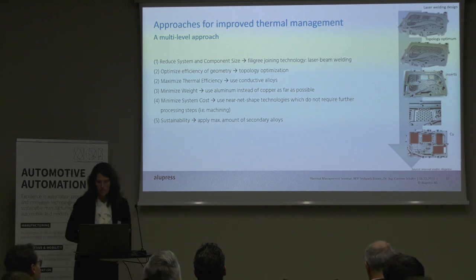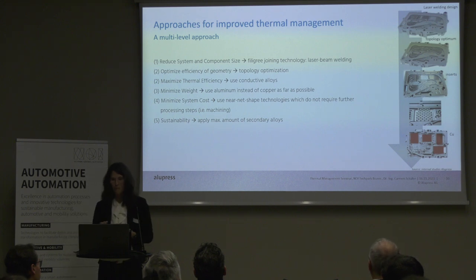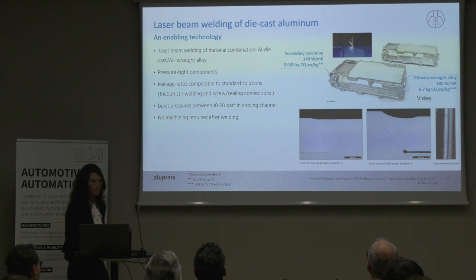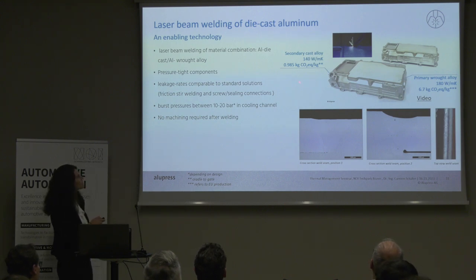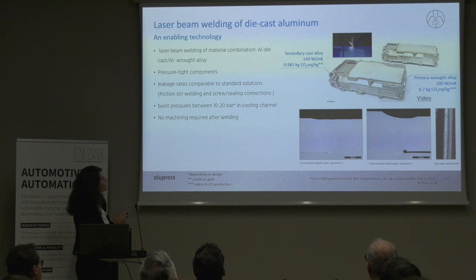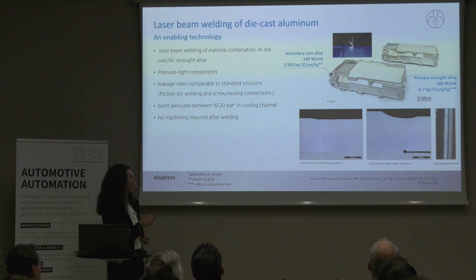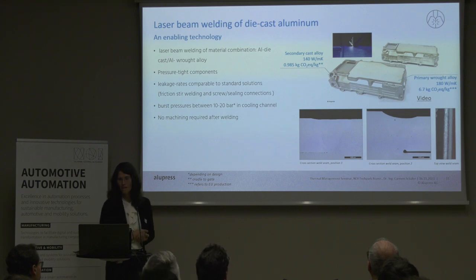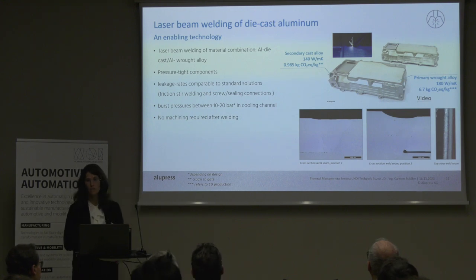And of course, everyone wants copper because it's a good heat spreader, but copper is expensive, copper is heavy. And this is like a hybrid heat sink where we apply a copper layer on top, so you could attach the electronics on this with soldering. And what's important is it's mostly a secondary alloy, which has good CO2 imprints, but also pretty bad heat conductivity. On the opposite side, what is usually used in liquid cold plates is a primary alloy, a wrought alloy, which has a very bad impact on CO2, but of course has very nice heat conductivity.